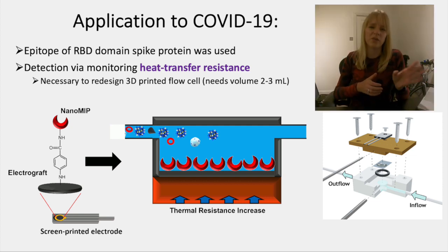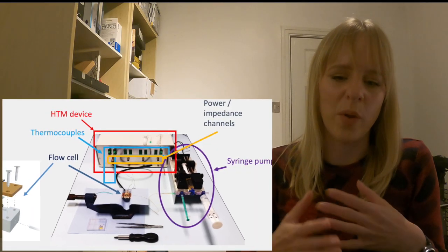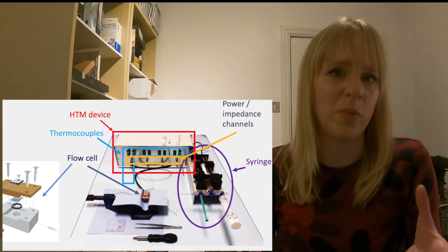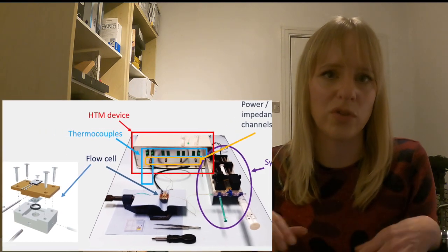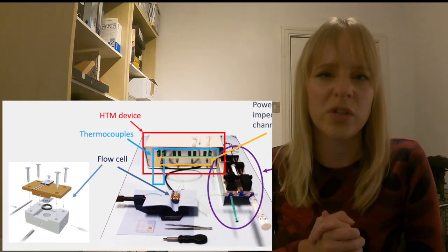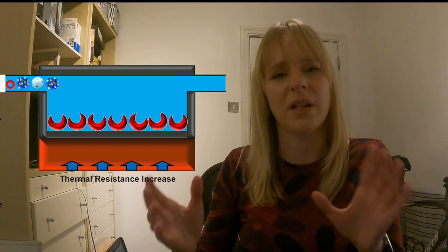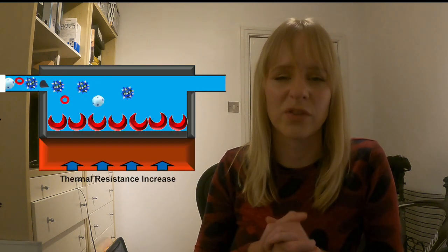What we did then is we've taken these nanoparticles and functionalized them into screen printed electrodes. And screen printed electrodes are very often used commercially, they're very low cost and they're disposable electrodes, so they're very suitable for commercial research. And as you can see here, we used our specific setup, which is based on this thermal detection of the heat flow that goes between the surface. As soon as we see that there was binding to these nanoparticles, there was a change in the thermal resistance.